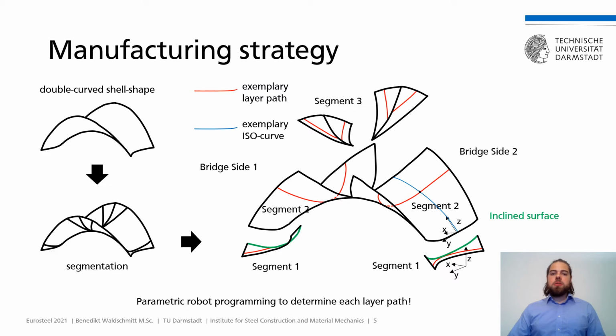As a next step, we had to evolve a manufacturing strategy. This describes the sequence and the direction in which layers are applied. As we had considered the challenge of a double curved shell shape, we had to divide the bridge into 3 symmetrical segments with different application directions and layer path, given on this slide. The first segment serves as the basis for the cantilevered second segment and forms a surface inclined by a 45-degree angle to the base plate indicated via the green line. Proceeding from this structure, new overhanging welding layers are applied.